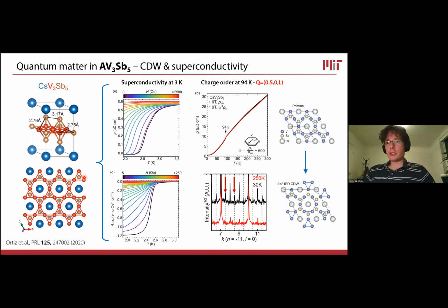So this caught a lot of attention and really a big spotlight starting a few years ago, thanks to the discovery of superconductivity and charge density waves in the very same materials. And I did a lot of work on the cuprates. So when I hear superconductivity and charge density waves and phase competition, I get very excited. And so it appeared from the beginning that this family of materials could be a new platform to explore different forms of electronic symmetry breaking and the competition between them. So superconductivity is happening at low temperature in these materials, at temperatures that vary between 1.5 and 4 Kelvin, whereas charge density waves or charge order has an onset which is between 70 Kelvin and 94, 95 Kelvin, depending on the alkali metal.